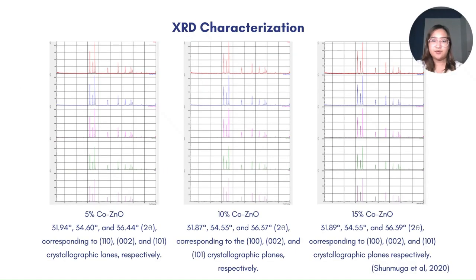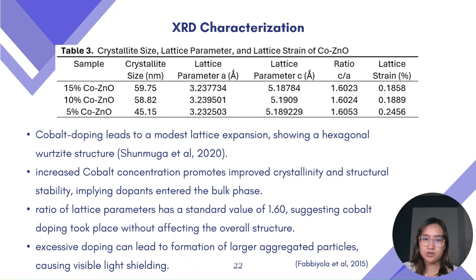Cobalt-doped zinc oxide samples reveal a hexagonal wurtzite ZnO structure with the three strongest reflections observed listed in this slide. These peak positions align well with standard zinc oxide patterns, indicating that cobalt ions are successfully incorporated into the zinc oxide lattice without the formation of secondary cobalt oxide or metallic cobalt phases. Table 3 summarizes the analyzed XRD results to express the lattice distortion and crystallite size of the Co-ZnO, where the values are calculated in accordance with the characterization study by Shunmuga et al.